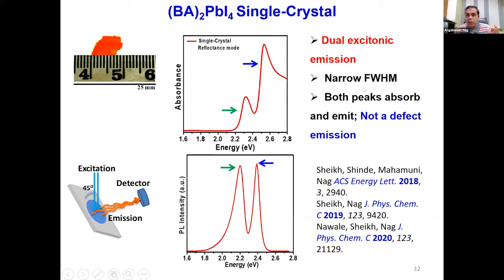If we compare the full width at half maximum of the emission peaks, lifetime, etc., we come to the conclusion that both the emission peaks are excitonic emission. This is a somewhat unusual situation, that from one single crystal you are seeing two excitonic emissions and two corresponding absorptions. It looks as if the single crystal has two band gaps, which cannot be possible. But importantly, we have made about 30 such compositions of layered perovskite single crystals by varying the organic cation, lead versus tin, and halides. All of them have this generic feature that they show two excitonic emissions and absorptions. If you want to see more of these examples, you can have a look at the papers that we published in the last couple of years.